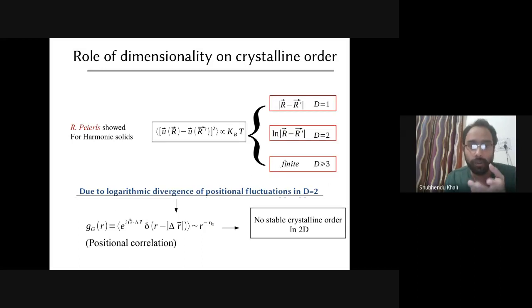But before coming to that question, a more fundamental question arises: whether in two-dimensional space a stable crystalline order can be formed or not. This question was first addressed by Rudolf Peierls. He showed that in a harmonic solid the positional fluctuation at a given temperature diverges as the system size in one dimension. It diverges logarithmically with system size in two dimensions and remains finite only in higher dimensions. Now, due to this divergence in positional fluctuation, the correlation function shows a power law decay. So this implies that there is no stable crystalline order in two-dimensional space.